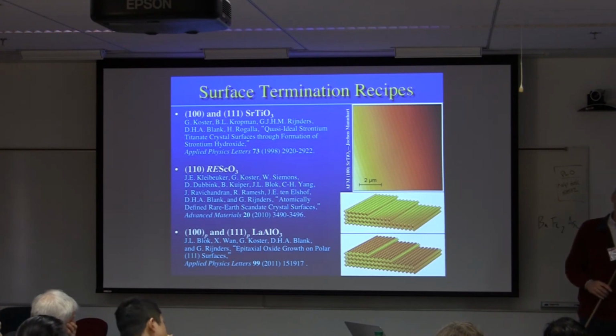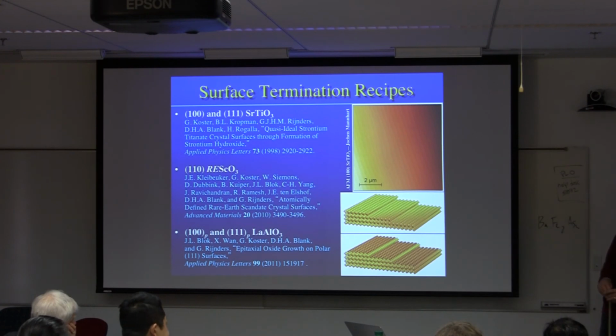On the substrate side, I'm happy to be part of a collaboration that's doubled the number of perovskite substrates in the last decade. And we keep adding more at about a rate of 1 per year. But if you look at other systems that maybe you're interested in, oxides, pyrochlores, there are 0 commercial substrates in pyrochlores. In spinels, there's 1. So there are all these other oxide systems that you might be thinking of playing this game in. There's a need for more substrates that have well-controlled surfaces.